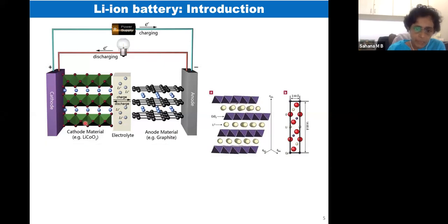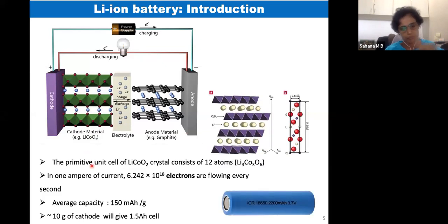And meanwhile, cobalt will change its oxidation state from 3+ to 4+. But now you can see this is a couple of unit cells. One unit cell is around 14 angstrom in the c-axis. So lithium cobalt oxide, basically the primitive unit cell, will have only 12 atoms. In that, there are only 3 lithium. So one lithium can maximum give you 1 electron. So one unit cell can only give 3 electrons.